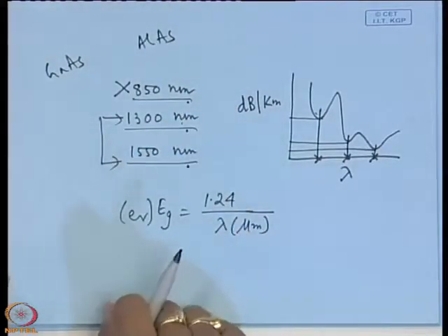Gallium aluminum arsenide is formed, but care must be taken that that material must have the lattice constant same as that of the substrate on which you would like to grow the gallium aluminum arsenide. So, that is a constraint. You cannot use any kind of substrate for any kind of material. Okay. One constraint is that.